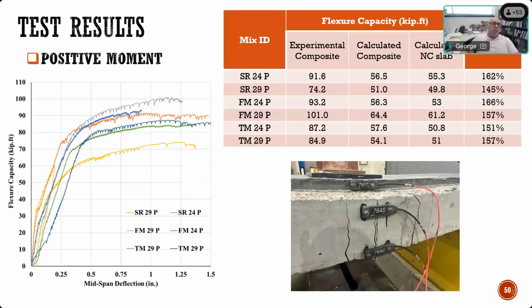And in all of them, we looked at the experimental value and the calculated one and the ratio between the two, and we always exceed the predicted capacity, or even the capacity for a conventional concrete, normal concrete slab. Significantly increase the capacity in positive moment and also in negative moment.